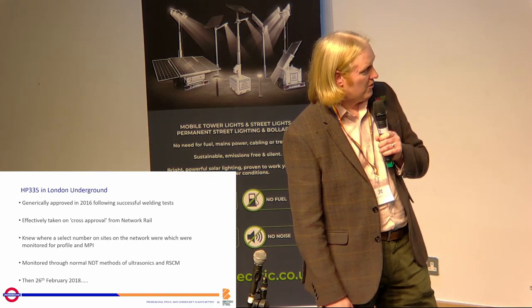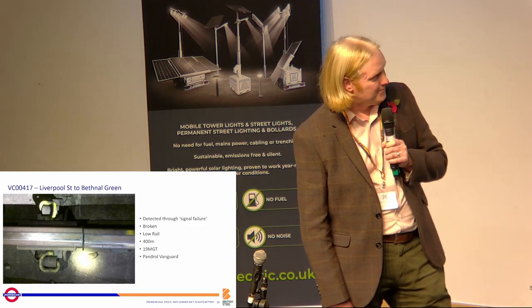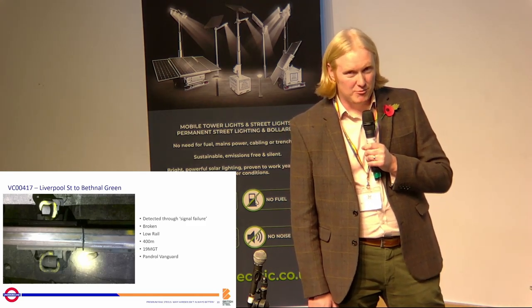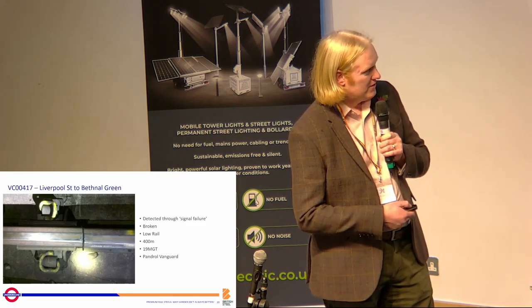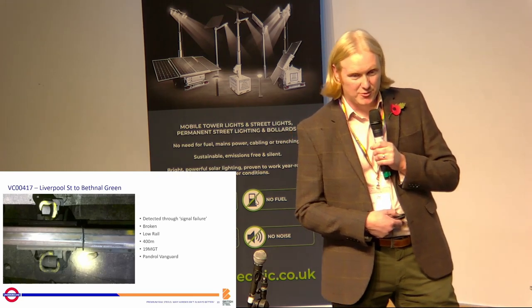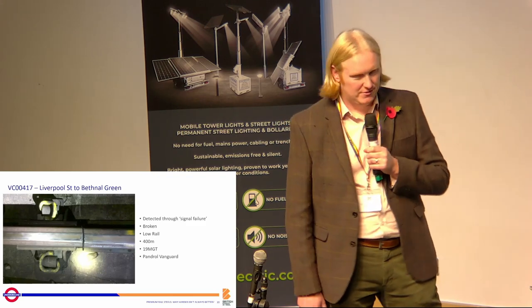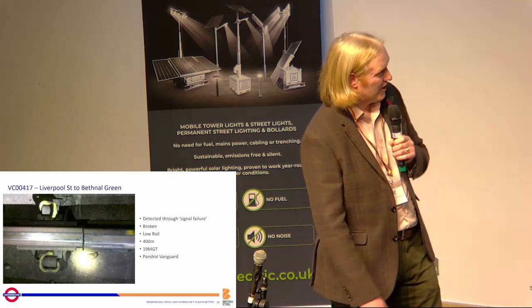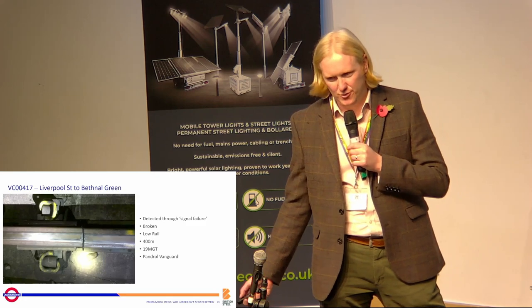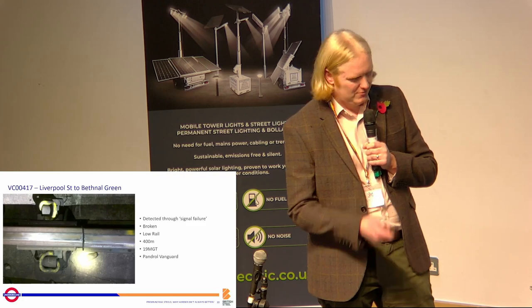2016 it's approved, and on the 26th of February 2018, this is what I woke up to — a photo sent to my email. This is Liverpool Street to Bethnal Green on the Central Line: a broken rail in HP. One thing you will notice, it's also on a track system called Pandrol Vanguard, which is a very vertically soft track form. Lots of issues with corrugation in this area — that's why it was put in. Low rail of a 400-metre radius curve, detected through the signalling system.